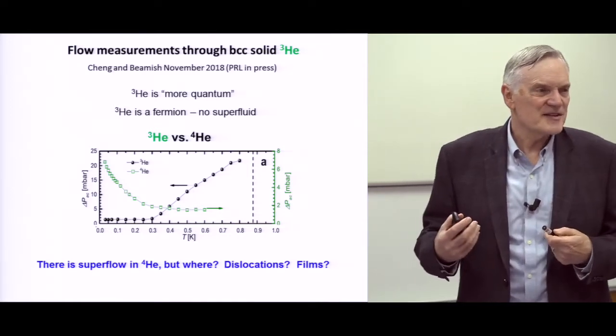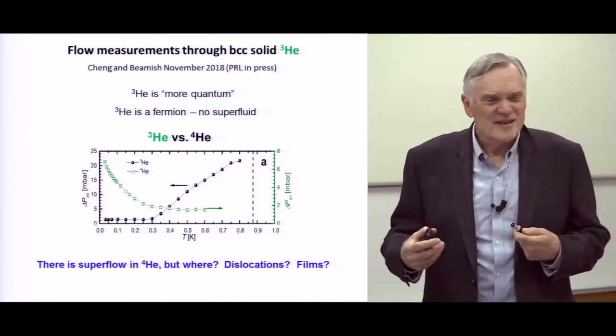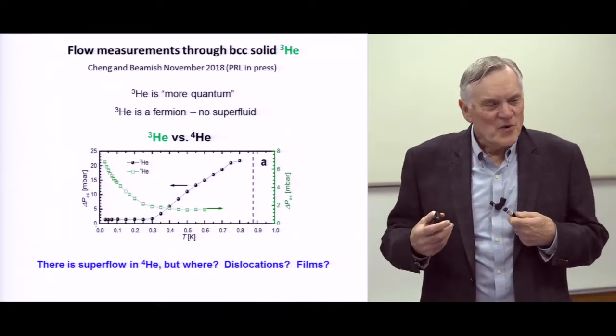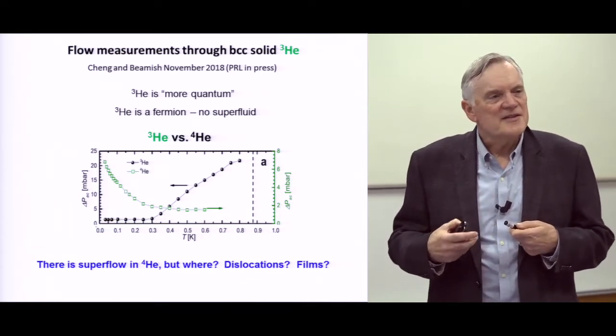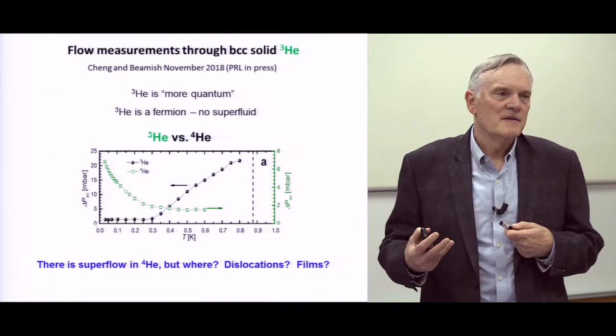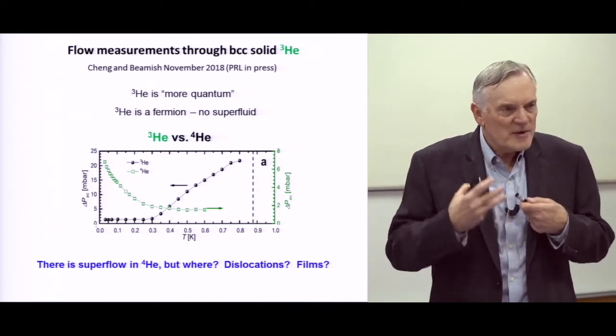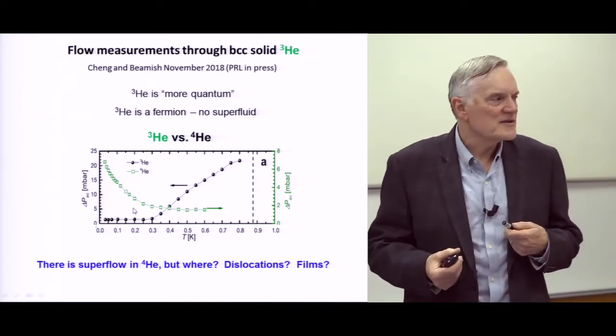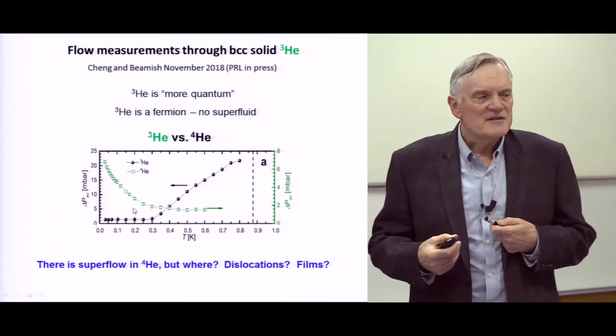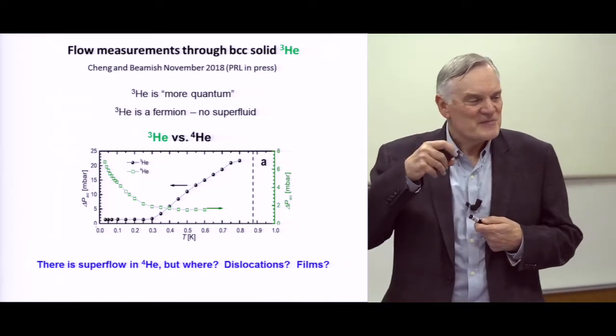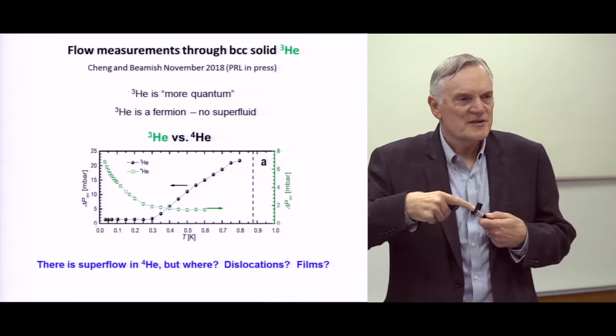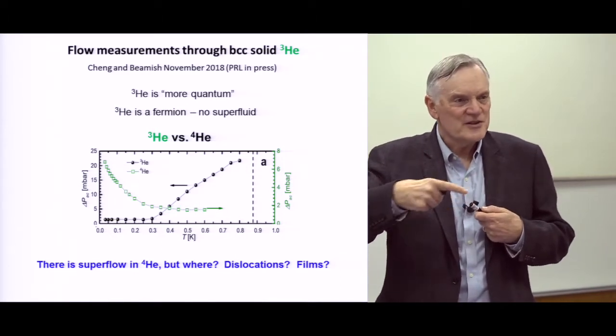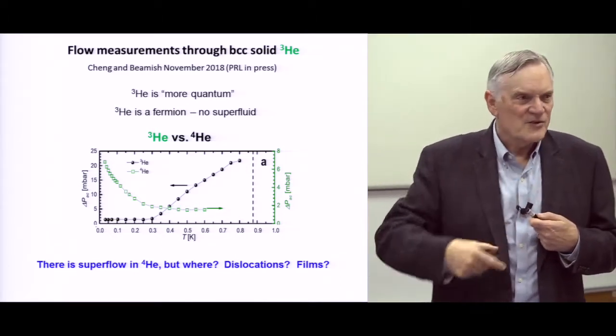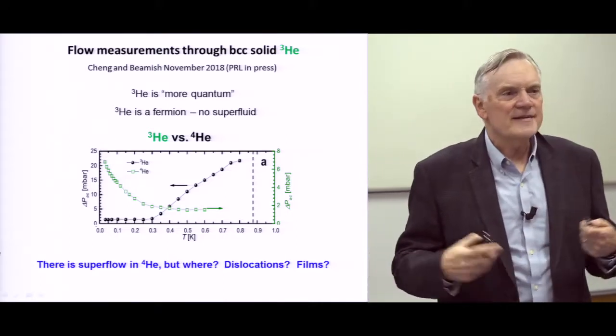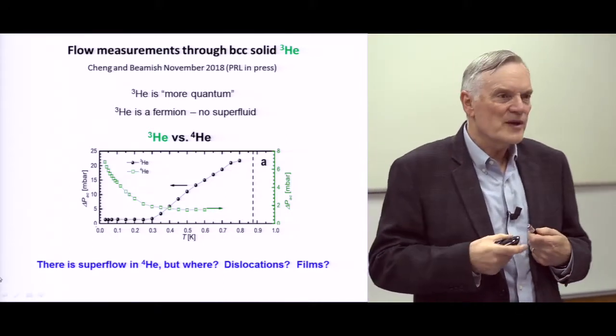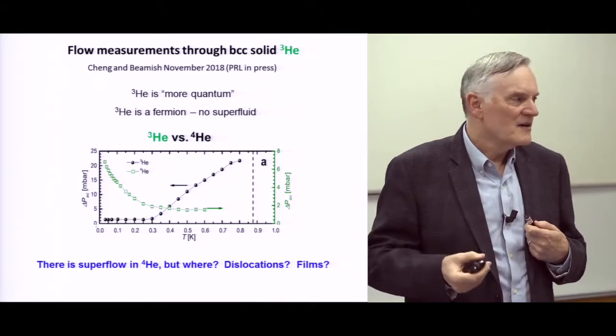The dislocations you can't see directly, we don't have an open cell. So the only tool we can think of is to see how much helium-3 it takes to block it. Because the helium-3 that you put in is not a lot, but it's got to be blocking it somewhere. And the problem with the dislocation model is, they have this picture, a helium-3 on a dislocation blocks the flow. Well, one helium-3 per dislocation is a concentration like 10 to the minus 18 or something. It takes virtually no helium-3 to block one-dimensional channels. So I'm concerned about that.